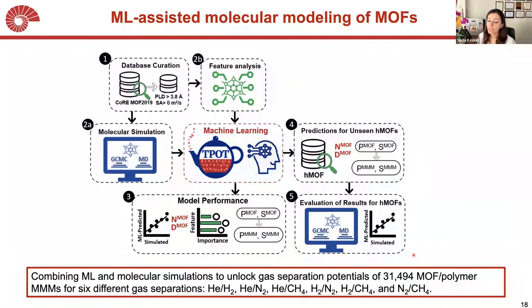So normally, imagine that we would be performing this number multiplied by 6 for 6 different gas separations, multiplied by 2 for adsorption and diffusion. This many simulations were required to unlock this many materials' performance. But here, we first did these simulations for a certain number of MOFs. And then we used machine learning to produce some models that can predict permeability of the materials. And then we used these models by studying unseen MOFs, which were not trained in the machine learning model.